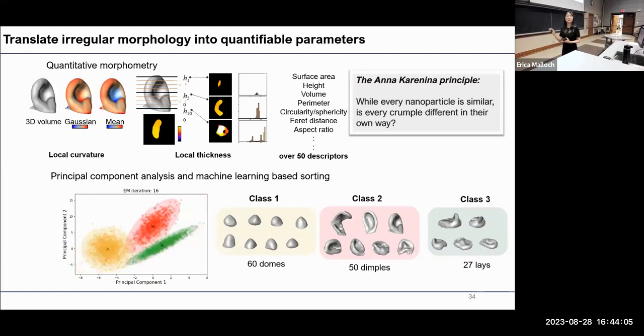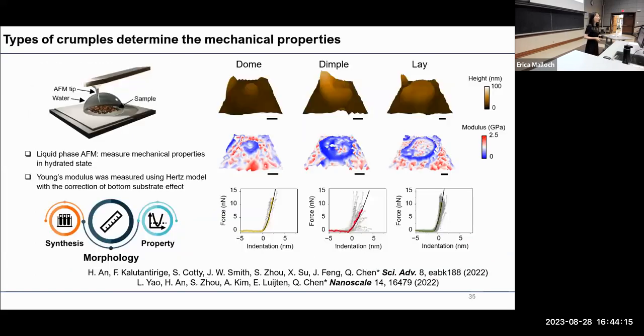And that's something you will never guess if you just look at the raw electron tomographs, because the crumples are so overwhelmingly heterogeneous. And then later we realized the types of crumples are closely related with a mechanical property we measure using AFM. We also show the portion of the crumple types can be fine-tuned by synthesis conditions. So this ultimately closes the loop of the synthesis, morphology, and property relationship. We really see this emergent relationship where the morphology serves as the middleman, linking synthesis and property, as very important, especially for polymeric materials at the nanoscale, because that's the nanoscale where chemical heterogeneity during synthesis and processing can actually happen.